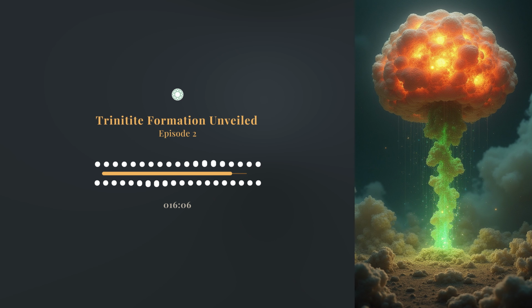Lead? Yeah. By measuring the isotopic ratios of lead in different microscopic areas, they could distinguish lead that probably came from the bomb components, which has a specific isotopic signature, from the common natural lead that was already present in the desert sand. I see. These kinds of details are absolutely critical for nuclear attribution, figuring out the specifics of an unknown device, maybe for treaty verification or investigating illicit tests. And you completely lose that fine-grained information if you just grind up the sample and analyze the average composition. It's just incredible that so much specific forensic data about such a complex event is locked away in the structure and chemistry of the glass it created.